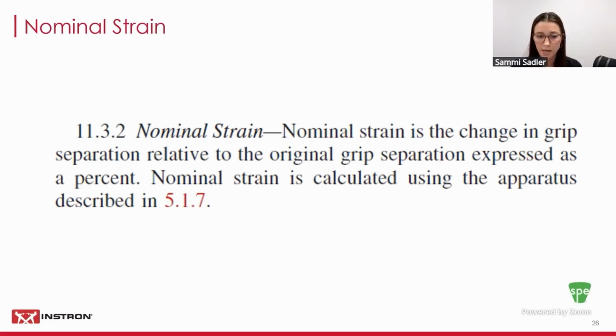If you're using a clip-on extensometer, the extensometer must physically be removed from the specimen before you can continue the test. If you're using an automatic extensometer, the software must be set up to remove the automatic contacting extensometer. And if you're using a video extensometer, it must automatically change the strain source from the video extensometer to the crosshead. Instron's Bluehill Universal software uses an algorithm that will automatically change the strain source for you. So it is very important to note that if you do not have this set up currently, you must set this up within your method.